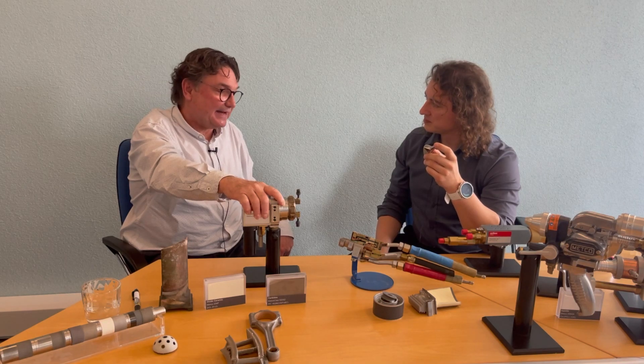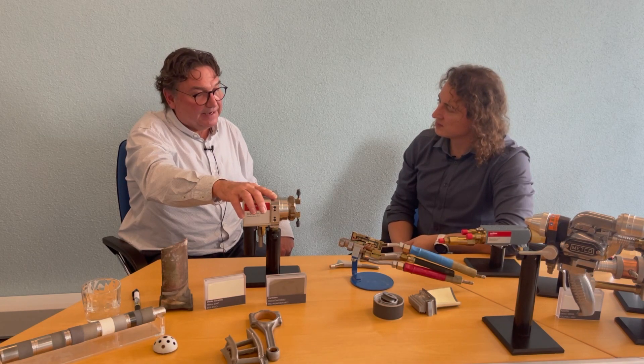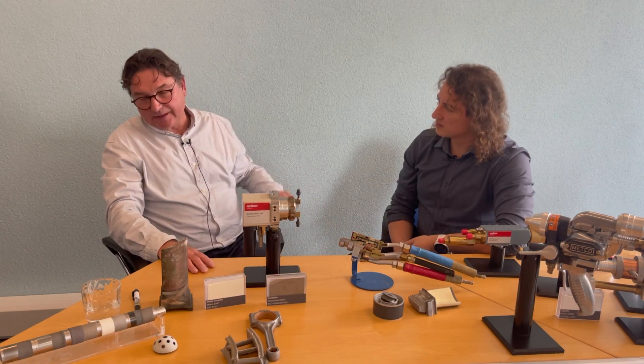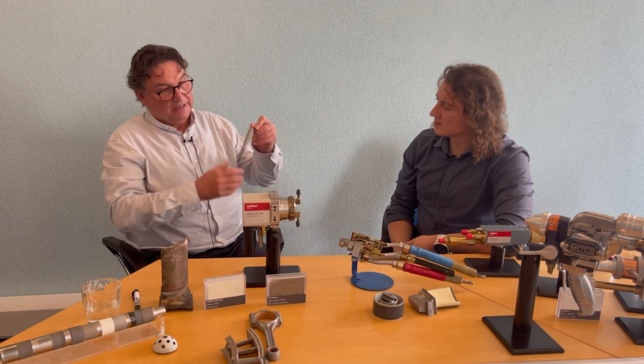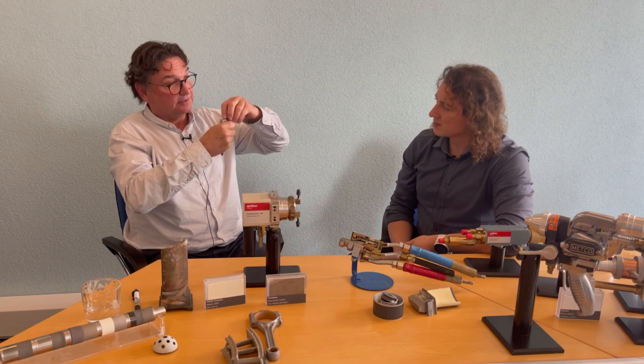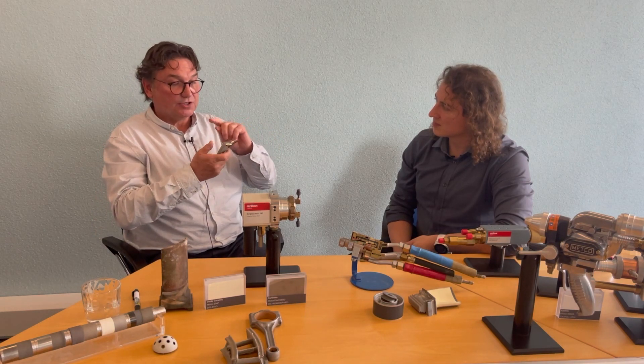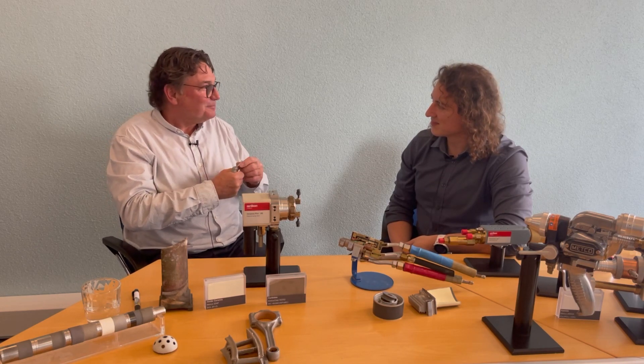It's not only hip joints — also knee joints and all prostheses are sprayed more or less with the plasma technology in controlled atmosphere. On the titanium biocompatible coating, we then spray hydroxylapatite — also with plasma, but in open atmosphere — which motivates the tissue to grow together with the implant. The big issue used to be that after a hip joint, the implant would start to loosen. But with the hydroxylapatite coating, the bone grows into the coating, fixing it — not cemented, but fixed.